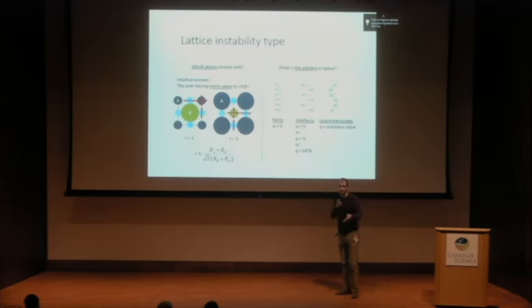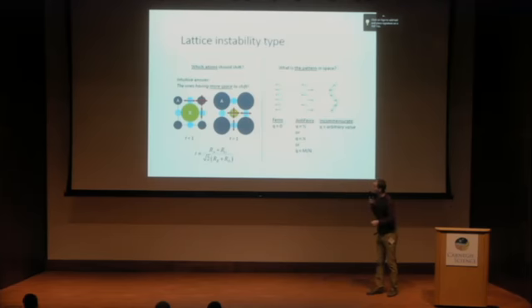Formally, it tells whether there is some free space for some particular ions. If it is less than 1, there is some free space for the A ion and for oxygen to move towards the A ion. If it is more than 1, the B ion is, let's say, almost free there. We know it is not strictly the case, but formally there is free space for it. And for oxygen, there is also an opportunity to move towards the B ion. I should draw your attention: it is not strictly a projection of the unit cell, it is, let's say, an artistic description, because if it were strictly a projection, I would have to plot one atom after the other. It is more difficult to appreciate. But I will use these diagrams throughout the talk. The tolerance factor is depicted at the bottom.